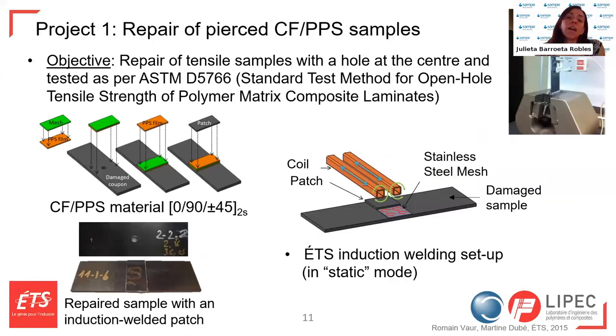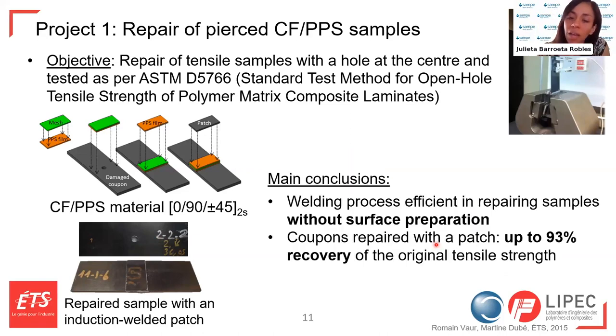Now, in terms of the most recent research that has been conducted, the École de technologie supérieure here in Montreal has explored using induction welding to repair specimens made out of carbon fiber PPS. So there were three scenarios that were compared: a baseline, a damaged specimen, which had a hole drilled in the middle, and a repair specimen, which had a patch that was welded using induction welding with a stainless steel mesh. And what researchers found after testing these samples under tension was that this welding process was efficient in repairing samples without any surface preparation. And the specimens saw a recovery of up to 93% when they were repaired compared to the original tensile strength.